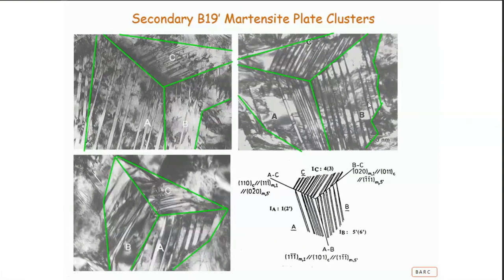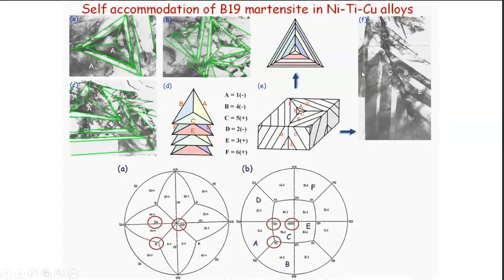And if I take nickel titanium copper, it's interesting because it is an orthorhombic martensite, so that monoclinic 96.8 is now 90 degrees, and it's an orthorhombic structure. And in these three plates which come together, one thing more interesting is that you don't have any substructure, because it doesn't require the lattice invariant shear in order to be an IPS. So this is a very ideal case where it's straight away an invariant plane strain, and you don't see any substructure, but you can nevertheless see these three plates, and they form a triangular morphology. What's more interesting about this is that it has actually 6 plates.